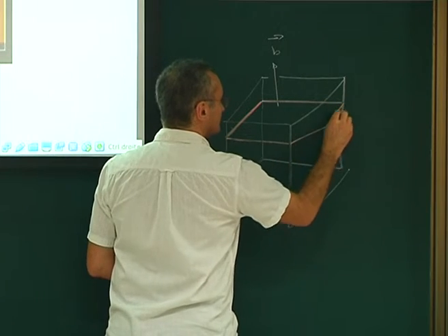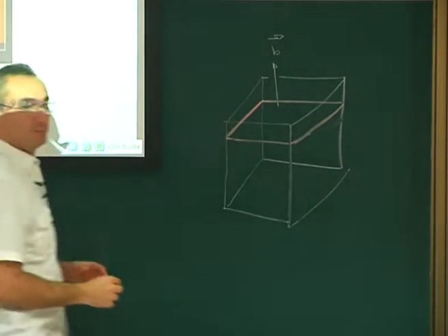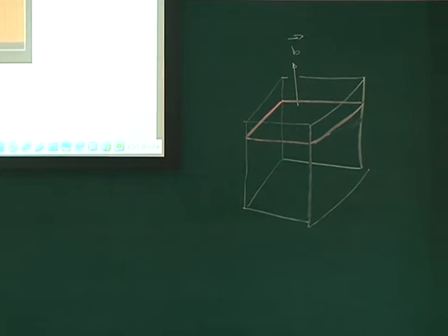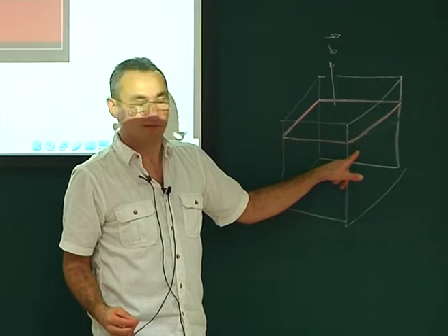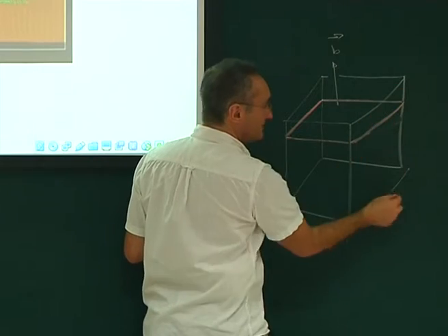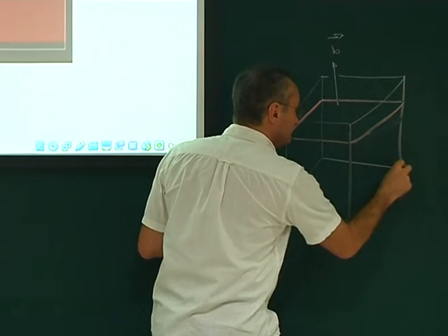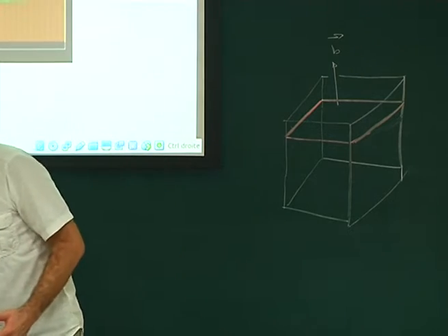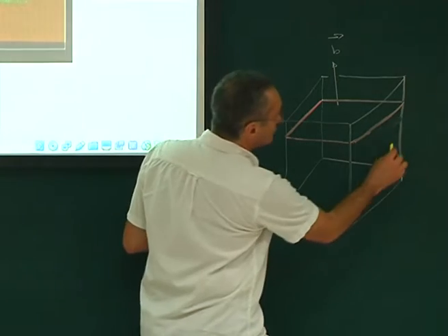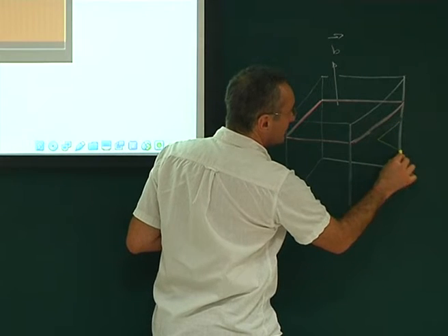So the loop, the final loop, will be like this. Do you see the loop? So the loop is made of what kind of segment? What is this segment? Is it an edge or is it a screw? This is an edge segment, okay? Indeed, this is an edge segment because it is perpendicular to the Burgers vector, and it is in this plane here. And if I were to plot the Thompson tetrahedron, I could locate it in that corner here. The Thompson tetrahedron is like that, okay?